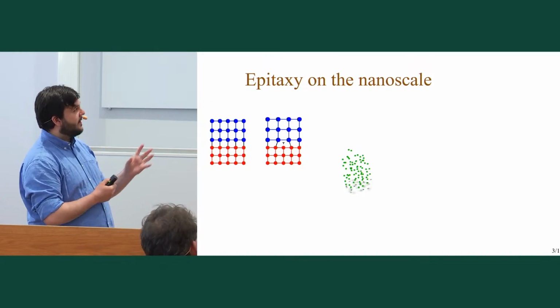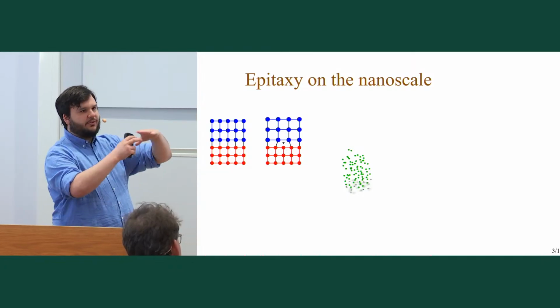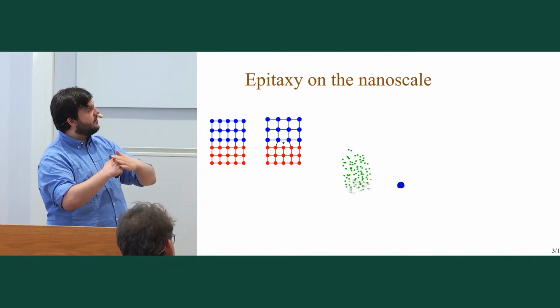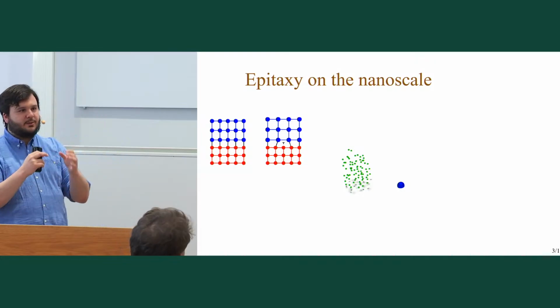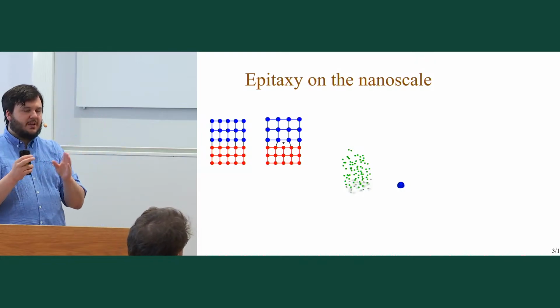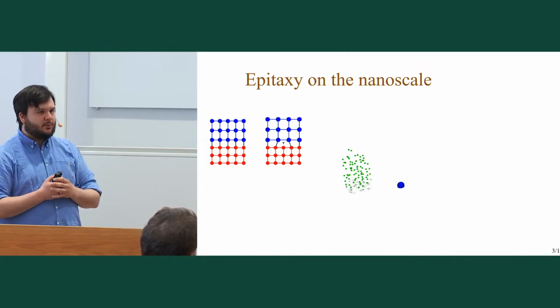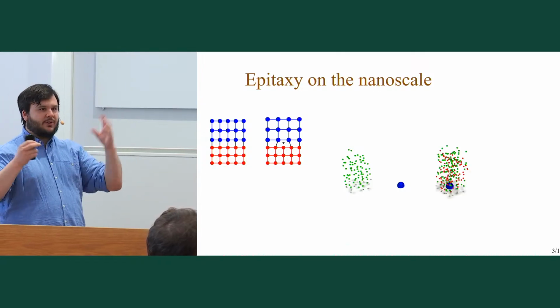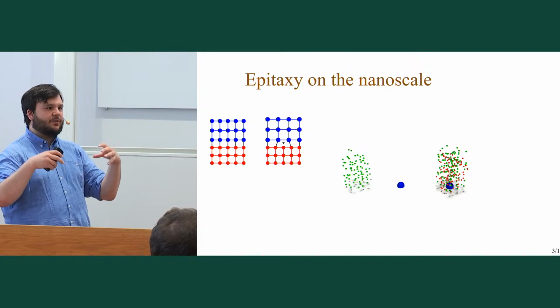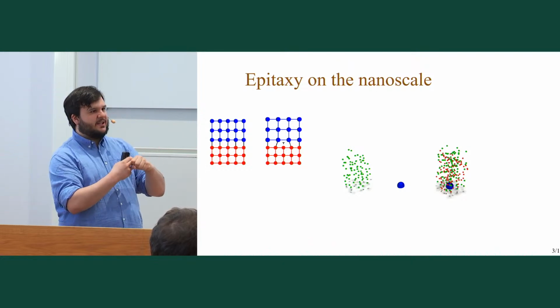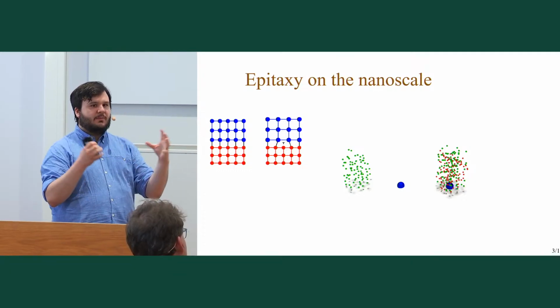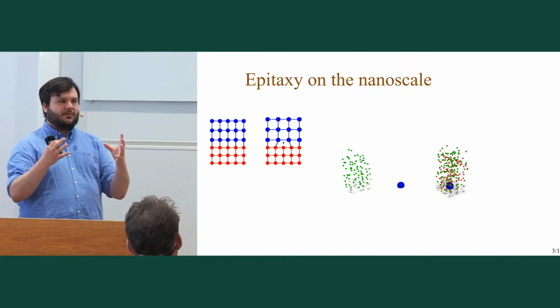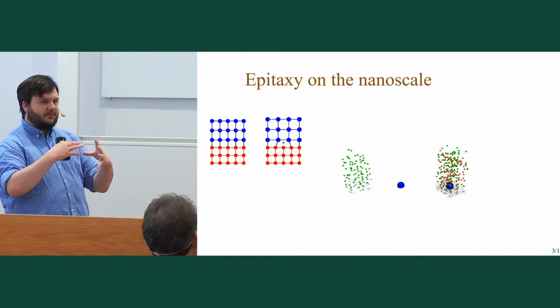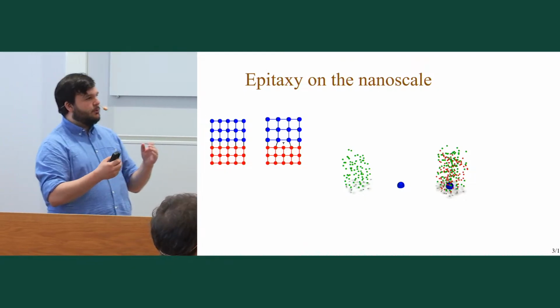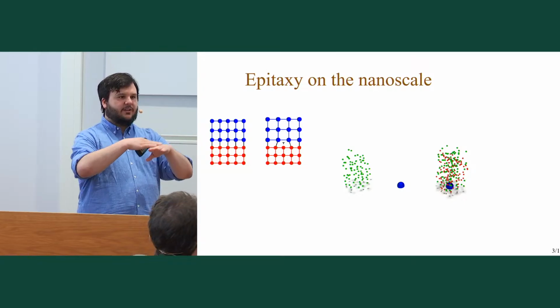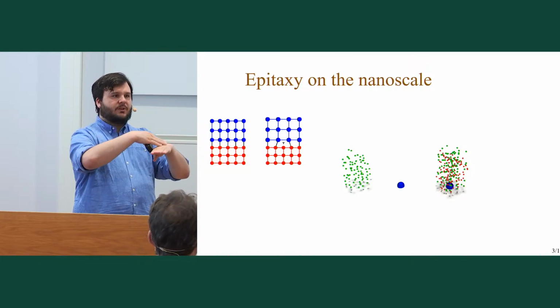So what I would do is I have a substrate, a surface, where I then come with a gas and I deposit a particle, which will be a nanoparticle in the order of 10 to 100 nanometers, and it will be liquid. And then I supply more gases, so I would supply zinc and phosphorus in gas form to this liquid nanoparticle. And when it becomes full of zinc and phosphorus, it will precipitate out some zinc phosphide. Now, it would preferentially do it at the interface with the underlying substrate. So that is where it will be easiest.